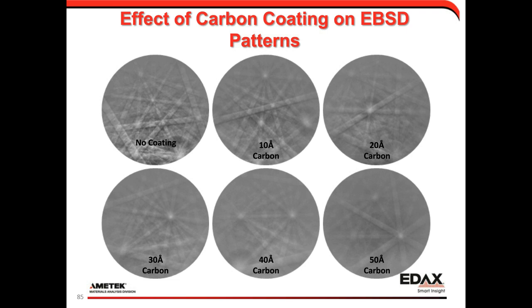And this just shows the effect of pattern quality by coating thickness. So there's a pattern with no coating and going up to 50 angstroms of carbon. You see we still see a decent diffraction pattern, and this is from an alumina substrate.